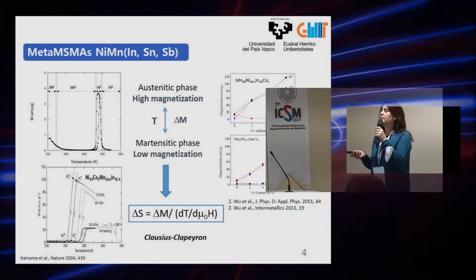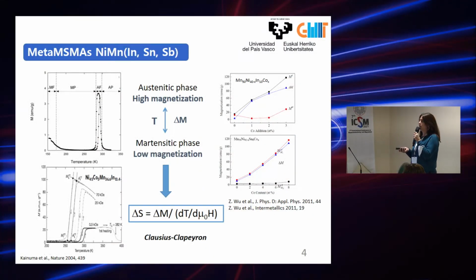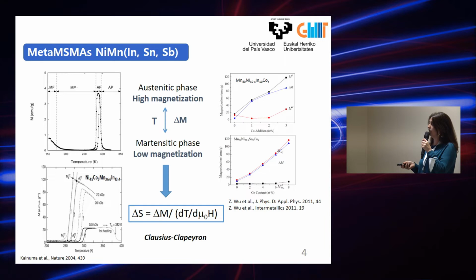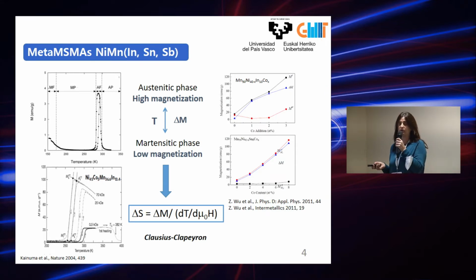And only to remember what the origin of this magnetocaloric effect is: we have this big jump in the magnetization when we go from our austenitic phase of high magnetization at high temperature to the low magnetization martensitic phase. And also, when we apply a magnetic field, we have this shift of the martensitic transformation to lower temperatures, and this is because there is an interplay between the temperature and the magnetic field that we apply. As a result, we can get an entropy change related to this change of magnetization, and also to the dependence between the temperature and the magnetic field applied.